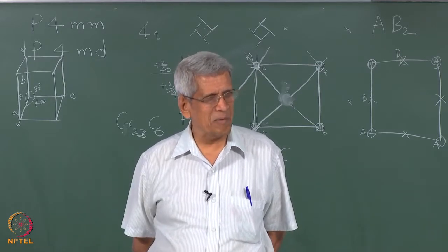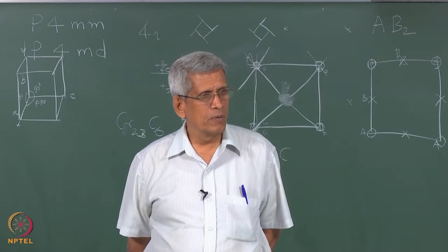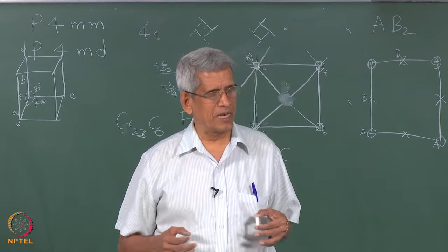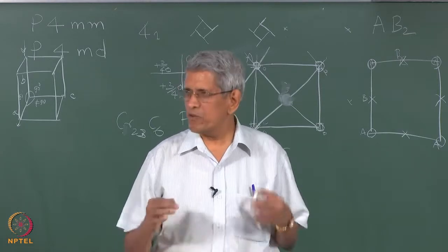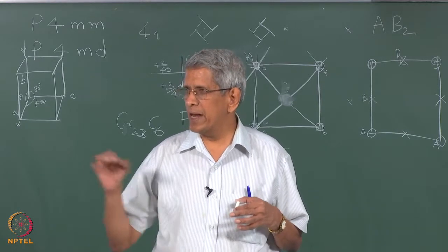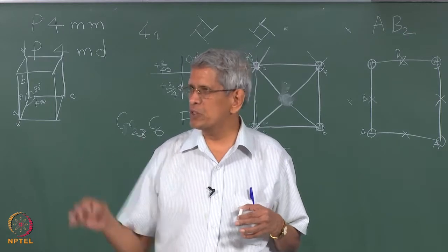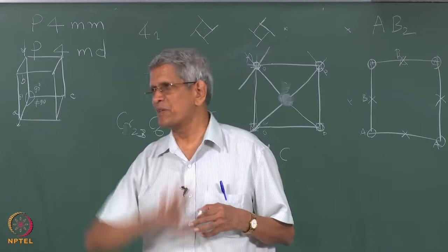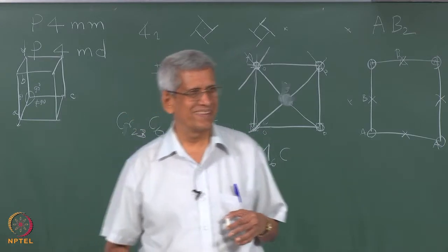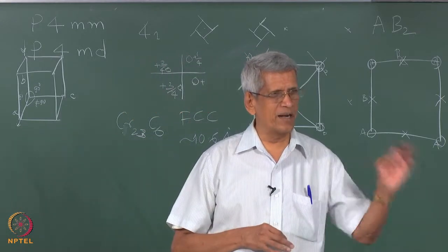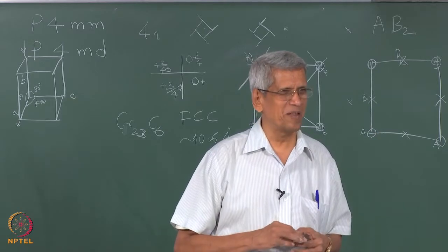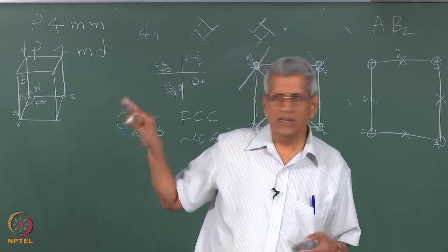Okay, these are three-dimensional lattices. No, I'm saying two-dimensional hexagonal. That means that when you study diffusional transformation, all diffusional transformation, how does it take place? By an atom coming and replacing another position and occupying it. In that, FCC to HCP is not possible, or from an ordered FCC to ordered HCP, it's not possible unless it is through a defect, shear or something.